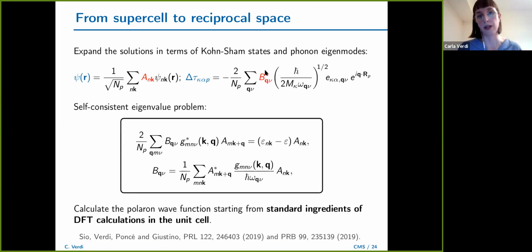If you do this, and you do quite a bit of algebra, which of course I'm gonna spare you, you get to these two equations, which is basically a self-consistent eigenvalue problem. And this can be solved, and you can obtain A and B self-consistently. And once you plug A and B into these expressions here, you have your polaron wave function and you have your atomic displacements. And I really want to stress that this can be done by simply using ingredients that come from standard DFT calculations in a unit cell. So you don't need supercells anymore.